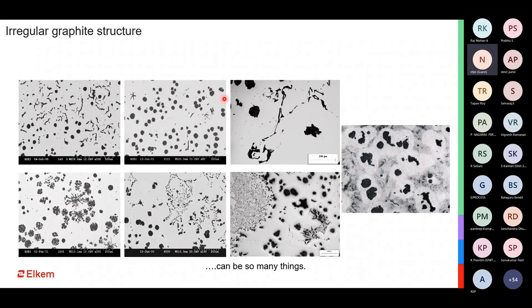There can be many forms of irregular graphite structure in our castings. We are aware that in case of ductile iron, one of the most important parameters is nodularity and nodule count. Nodularity is the roundness, the sphericity of the graphite nodules that we have, and nodule count is the total number of nodules that we have in the system. Of course, what we want is a very high number of nodules and also a very high percentage of nodularity, but it is not always the case. We sometimes encounter defects like you see here, which we will look at in detail during the presentation, which can cause other problems inside the casting.